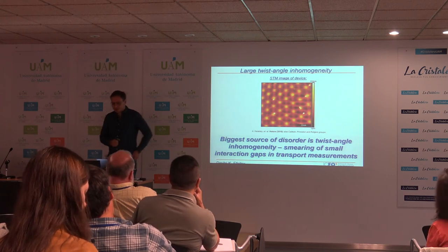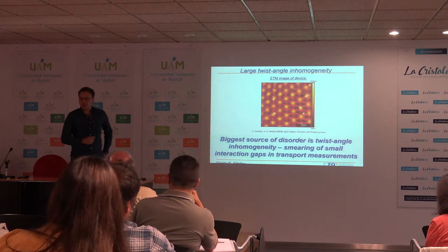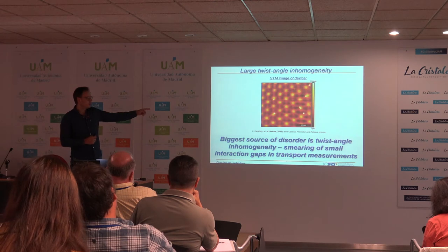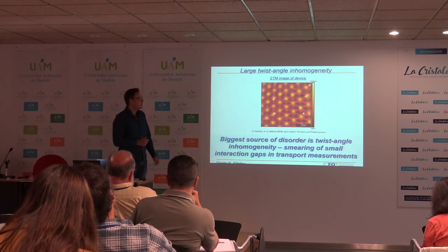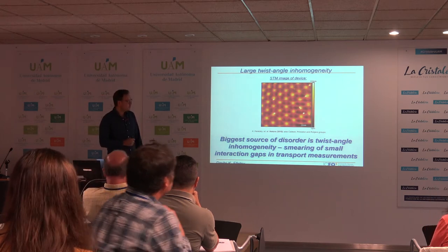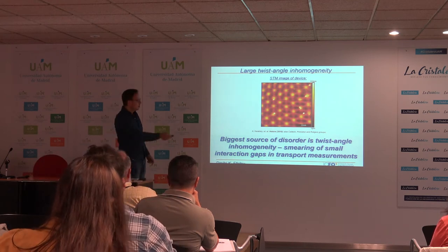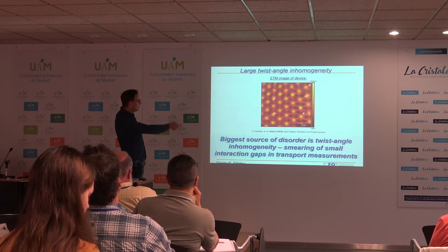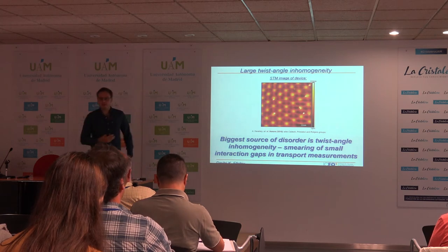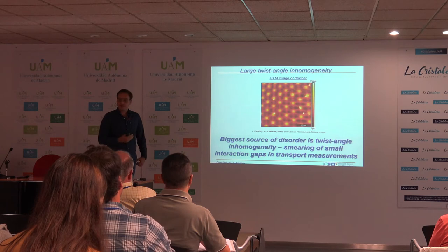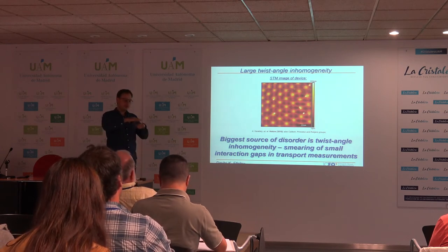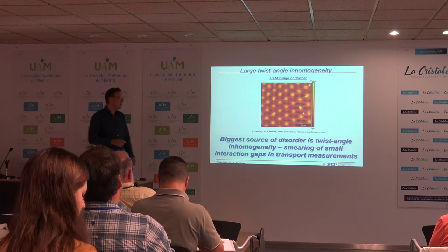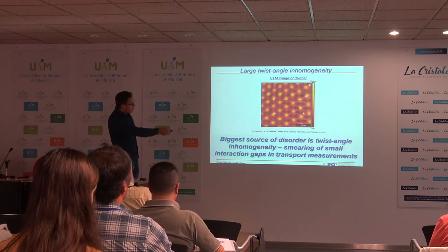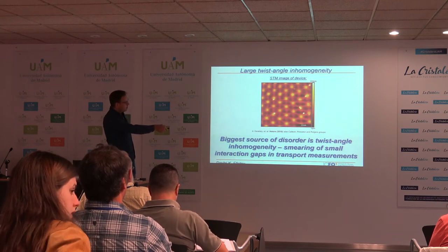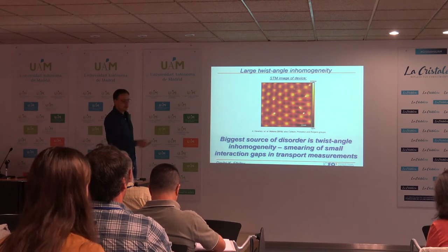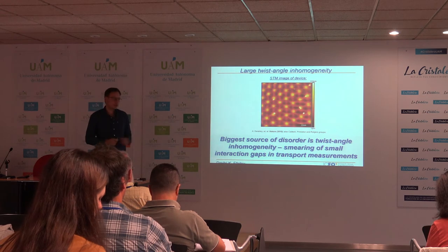Okay, so as I already mentioned, what is twist angle inhomogeneity? You can think of it as shown in this STM image from the Columbia group, where they image a typical twisted bilayer graphene device and can see the moire lattice. This image is not that big, about 100 by 100 nanometers. Basically, they measure the height map of the graphene, and typically we find that the AA regions have a slightly different height, probably because the atoms like to repel each other more in this region. The yellow dots you see here are all AA regions, and they are connected through these AB regions. So you get this perfect triangular lattice, the moire lattice of twisted bilayer graphene.